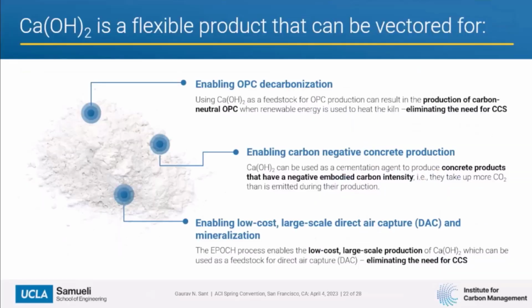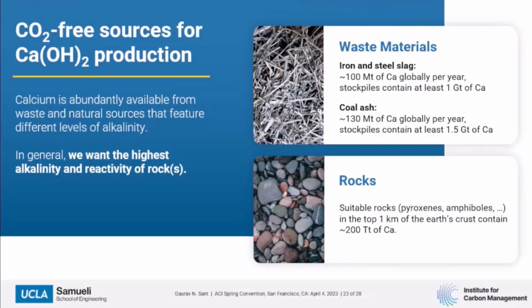So calcium hydroxide is actually really, really attractive for a variety of reasons, right? Not only can it enable OPC decarbonization because you can start to eliminate the need for using limestone, but you can start to use calcium hydroxide as a cementation agent to produce concrete, right? So this is based on the carbon belt strategy. But if you take a further view out, you can start to use calcium hydroxide as a low-cost sorbent for direct air capture. Turns out to be really important because if you can use existing infrastructure that's in place to produce low-cost sorbents, this will allow you to eliminate the need for CCS within the context of many cement plants.